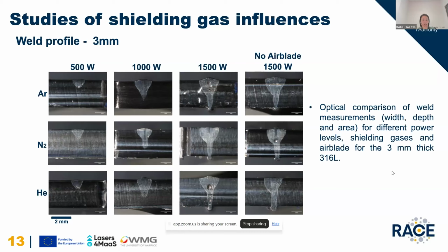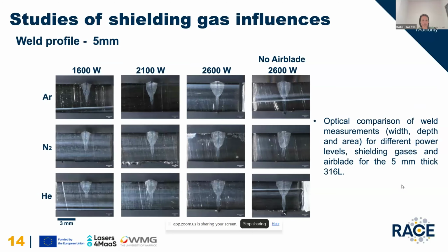This is the 3 millimeter we tested. We could see some of the pores generated, though some of the cross-sections actually look very clean, and we can also compare the penetration depth of each weld. This is the 5 millimeter as well. Interestingly, we didn't achieve full penetration using the nitrogen gas. However, we achieved it using argon and helium.